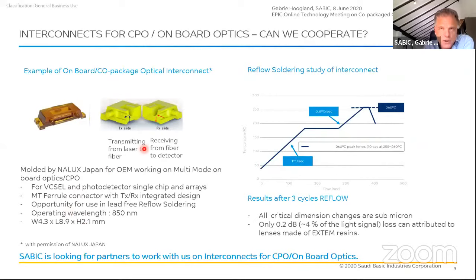These parts we just molded a few months ago. We have done some reflow soldering tests and we looked at 2 things. We looked at dimensional changes after reflow soldering, and we found that the delta in dimensions is very, very small, 0.1, 0.2 micron, which is more than good enough for multi-mode optics. But we also looked at signal loss in dB because of these Axtem lenses. I wouldn't say it's negligible, but it's a very low amount of signal loss, 0.2, 0.3 dB. So that looks all very promising.